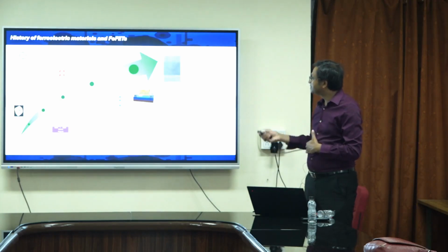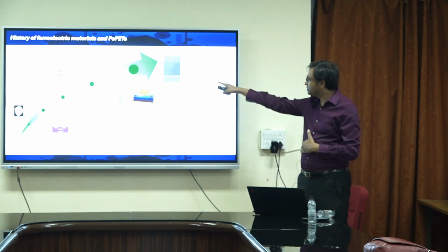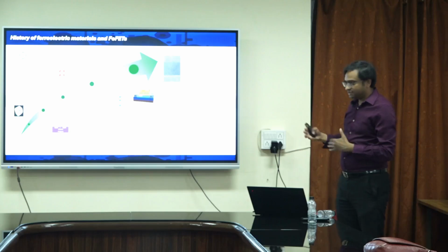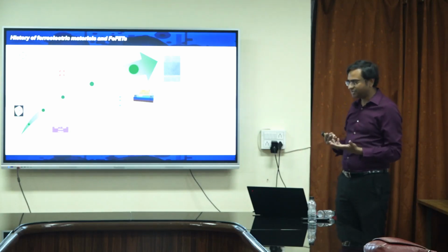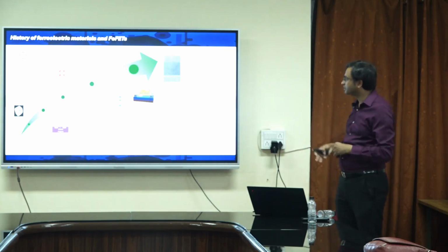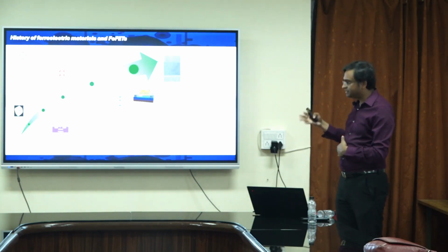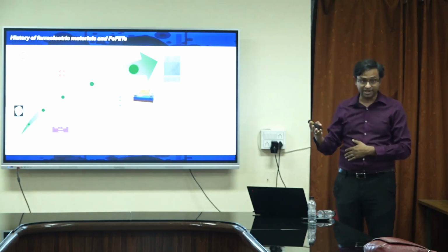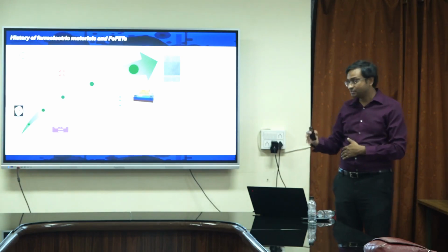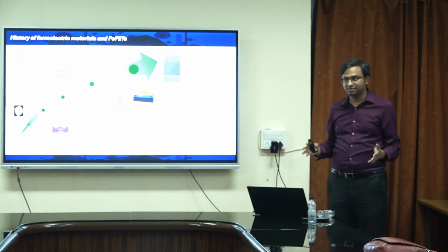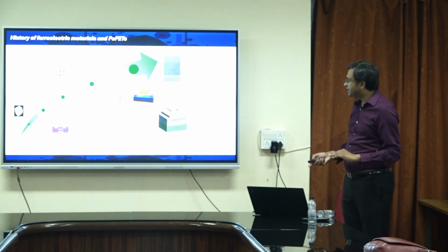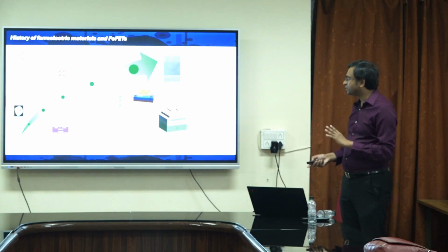Right, so this is an HfO-based FEFET. You can see the atomistic imaging. You can literally see the silicon atoms. This is a cross-sectional TEM. These oxides are mostly amorphous, so you will not see a really nice crystal structure over there. But as I told you, even with HfO, you actually have to heat it at a very high temperature to make it ferroelectric after it is deposited, and that is mostly not allowed once the silicon transistors are made. There is a back end of the line limitation. And this is exactly why some of the 2D materials are going to be very important.